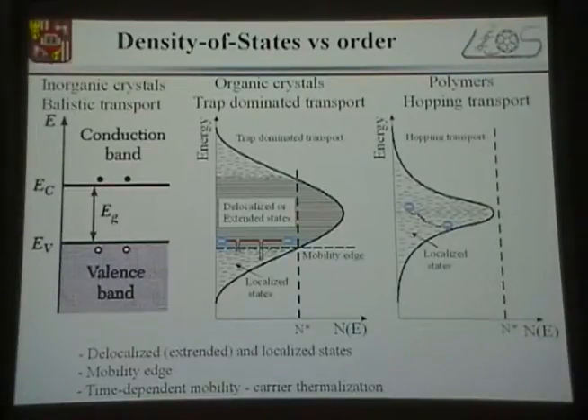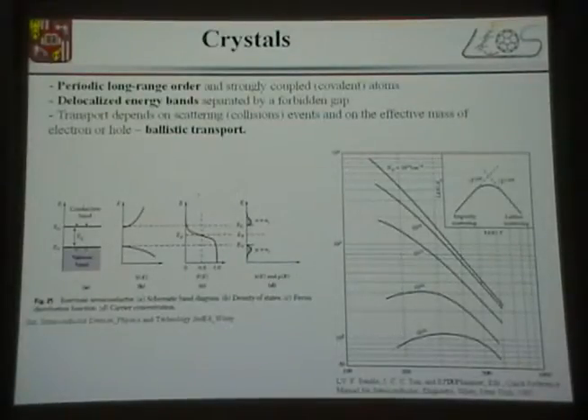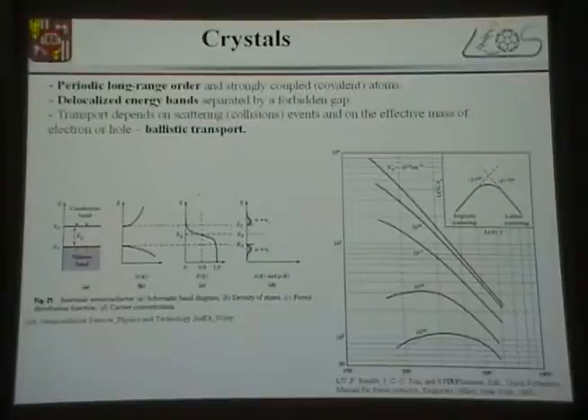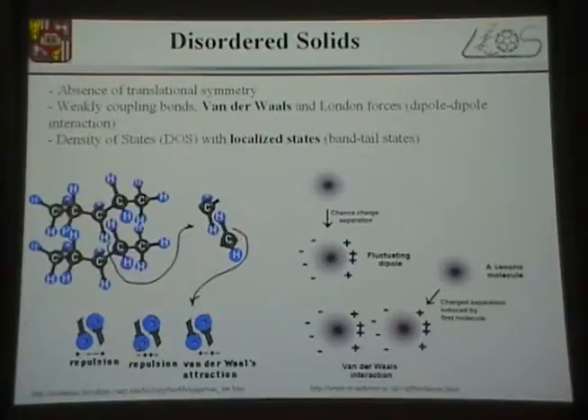So most of the time, we assume that the charge carrier transport in polymers, organic materials, is of this type. So it's completely disordered, hopping transport, where the electron hops from one localized state to another without having the possibility to be transported in delocalized states. In the crystals, as I already mentioned, transport is ballistic, so the electron undergoes scattering events, scattering between the atoms or vibrations. And the interesting thing, if you look at the charge carrier mobility as a function of temperature, depending of course on the doping concentration, those of you who are physicists who had a solid state physics course know it: mobility is increasing when the temperature is decreasing because of fewer scattering events. This is the well-known charge transport phenomenon, well studied and well understood.